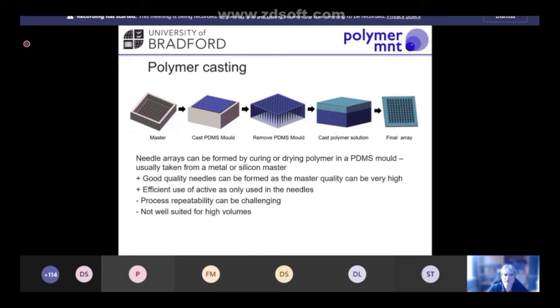As I say, you've got an efficient use of the active ingredient, as you only need to fill the needles themselves, then you can apply a backing plate onto that for applying to the area. The challenge here is it's a batch process, and process repeatability can be challenging. With the consistency of the molding here and then the second molding stage, you might get wear on PDMS molds. So do you use them once or do you keep taking them from the master? It's just a bit difficult to ensure repeatability over high volumes of manufacturing using this particular system.